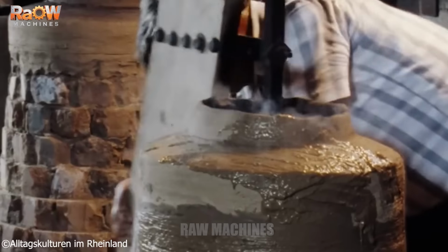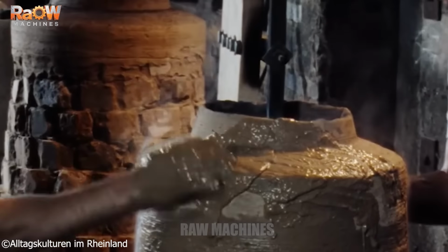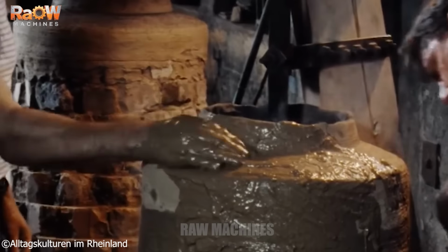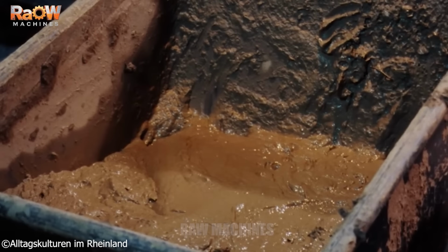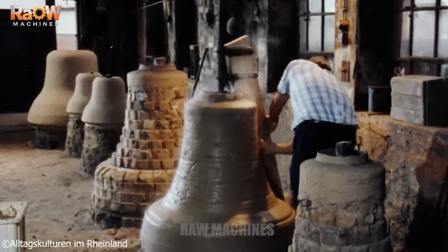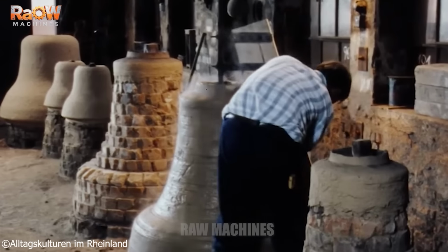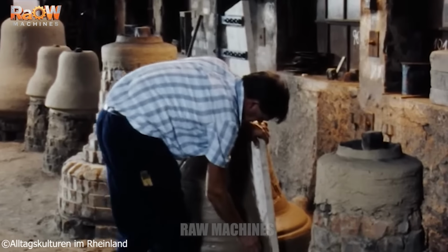The first clay layer applied at the base of the core consists of stiff clay reinforced with jute fibers. This layer increases structural strength, reduces the risk of cracking during drying, and provides a solid bond for the layers that follow.